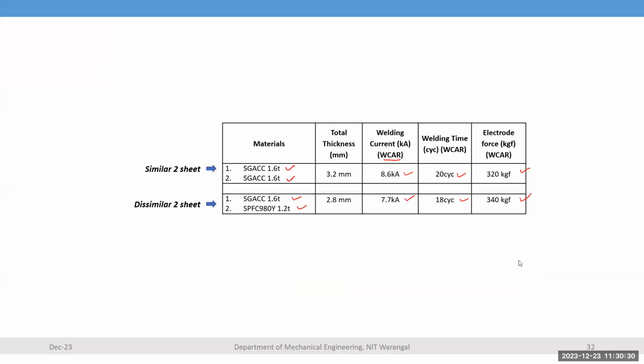For this case study, we have taken 2 sheets of similar materials and 2 sheets of dissimilar materials. That defines the thickness ratio. The thickness is 1.6 for both sheets when similar, the same thickness, but for the dissimilar kind the sheet thickness is different, 1.6 and 1.2, so that the total thickness of the entire nugget formed is 3.2 and 2.8. The welding current applied during the resistance spot welding is 8.6 kiloamperes and 7.7 kiloamperes. Then the welding cycle time is 20 cycles and 18 cycles.